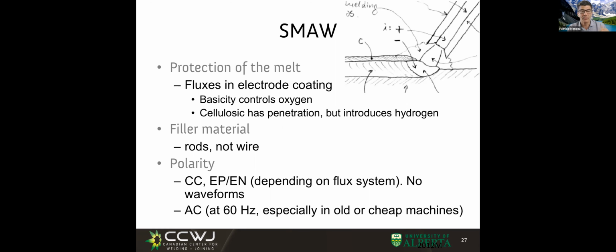Originally, something people observed way back in time when they were starting with electric welding is that rusty electrodes behave better than clean electrodes. Now, in these cellulosic electrodes, having moisture is helpful and it's not much of a problem because we already have hydrogen anyway. There are other types of electrodes that are low hydrogen and for which you don't want any moisture, and you have to keep them in an oven so they dry out and have the minimum possible amount of moisture and hydrogen.